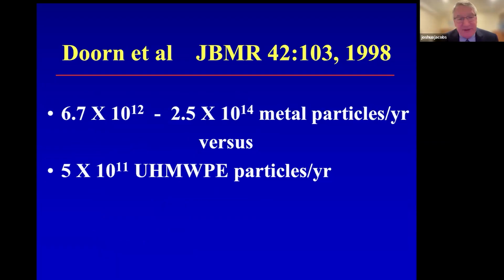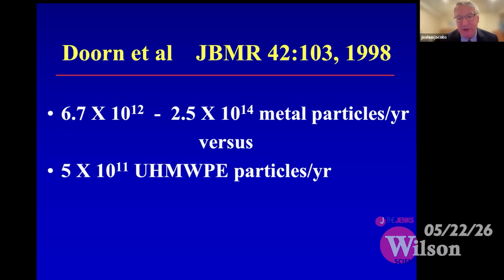And given that the mean particle size for polyethylene is about 10 times that, 500 nanometers or 0.5 microns, even though the volumetric wear rate may be 1 to 2 orders of magnitude less with metal-on-metal bearings versus metal-on-polyethylene bearings, actually the number of particles generated can be 1 to 3 orders of magnitude higher depending on what the mean particle size is. So it begs the question, what dictates the bioreactivity of the particles? Is it the number of particles? Is it the size of particles? Is it the surface area, the aspect ratio? Is it the surface configuration? All of these things are what I would call nanoparticulate biology that we're just really scratching the surface of.